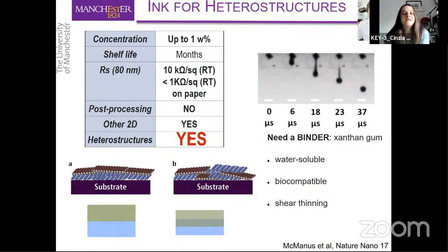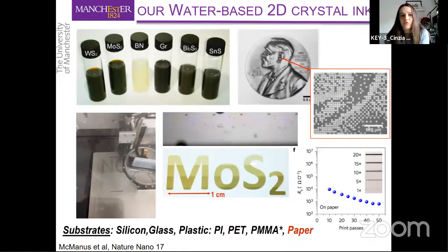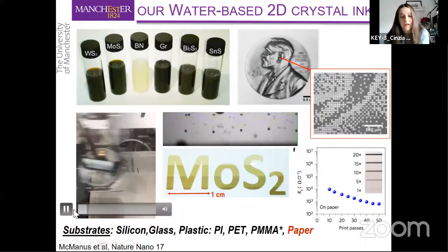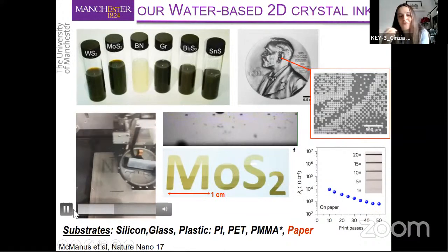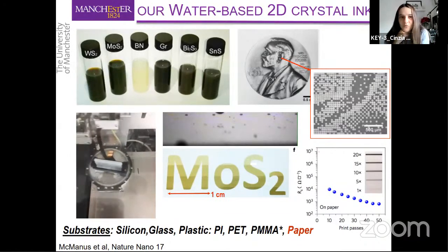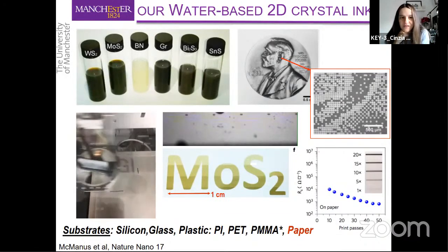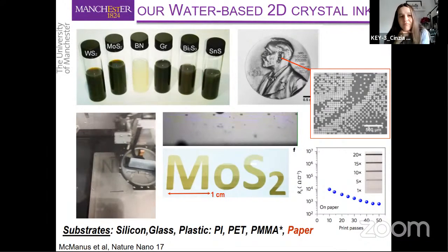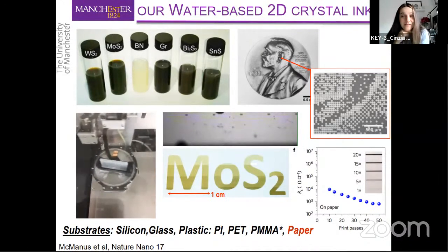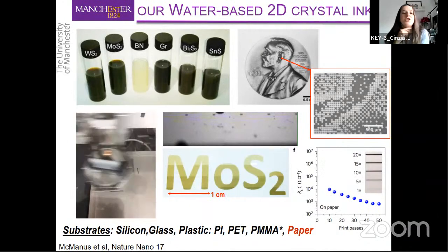Okay, so with this simple modification of the inks, we have been able to produce inkjet printable inks of different 2D materials, and they are all printable. There is no unstable droplet formation. They can be printed for months and months in the same cartridge. There is no precipitation or reaggregation of the material in the cartridge. Typically, one will be able to print for at least 6 months with the same cartridge.